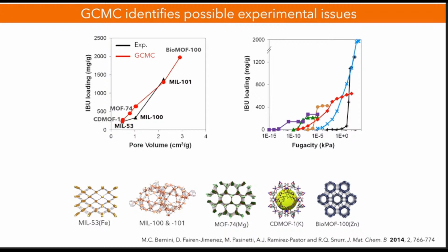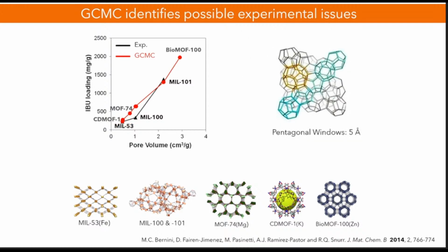This is interesting because, again, we can have a detailed picture of the adsorption phenomena at the molecular level, and this is how the material looks. This is the crystalline material with different mesoporous cavities. Something we did was try to block the access of the drug molecules to the smaller cavities that we have here. We block this porosity, and we can run the molecular simulations again. In this case, you can see the new simulation was much closer to experimental data.